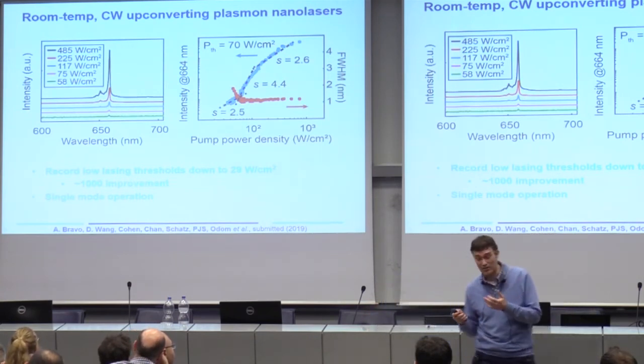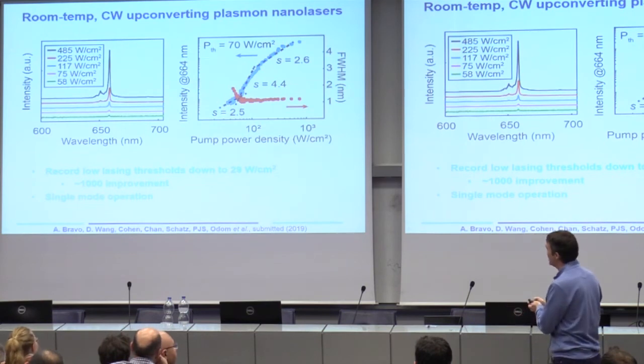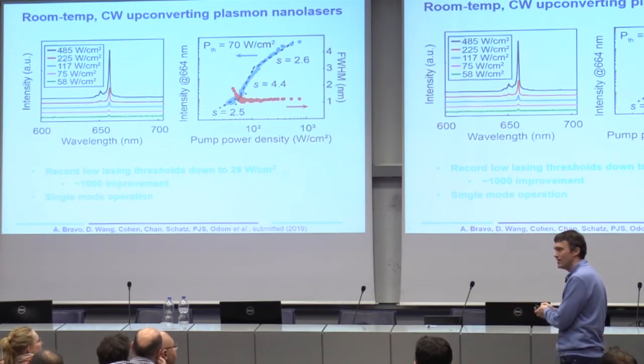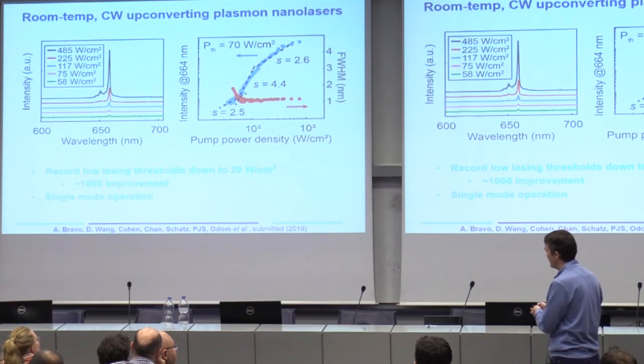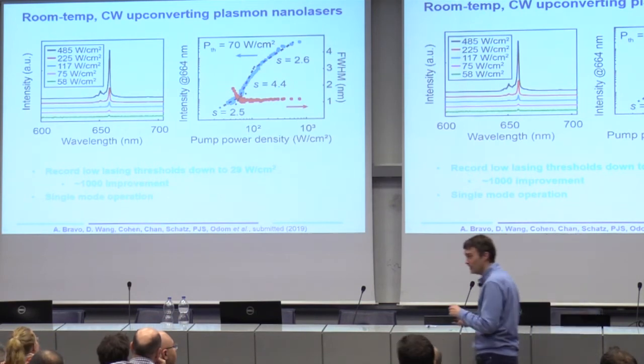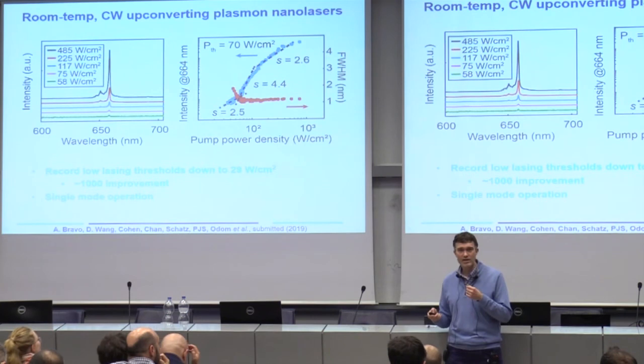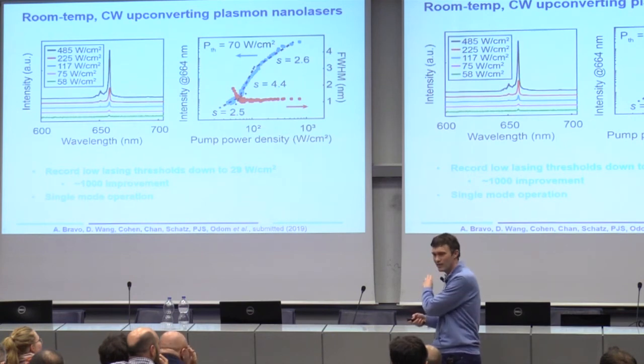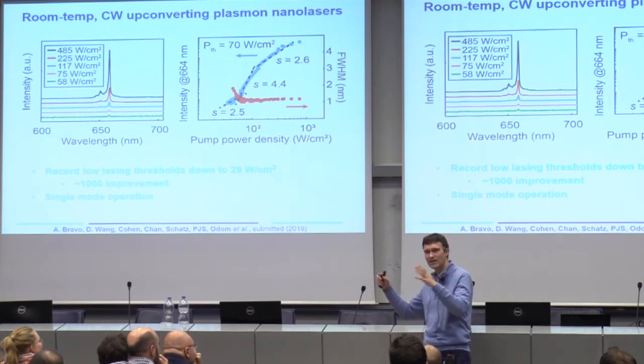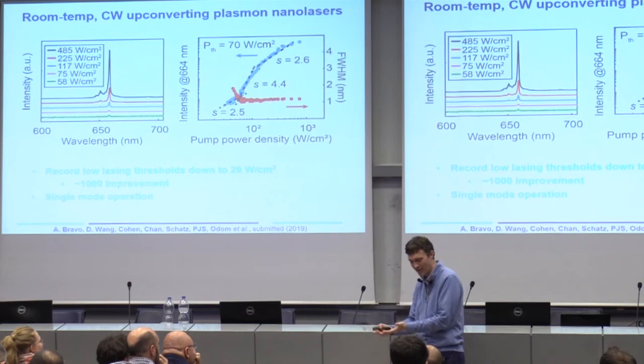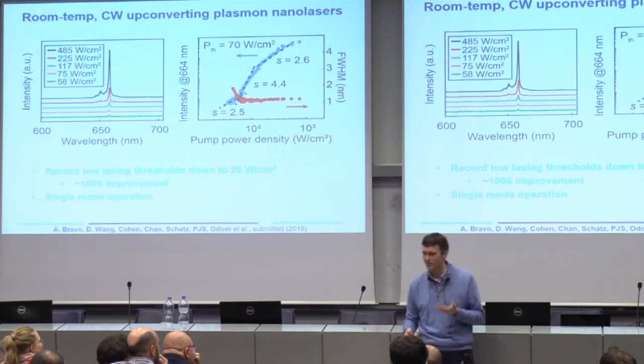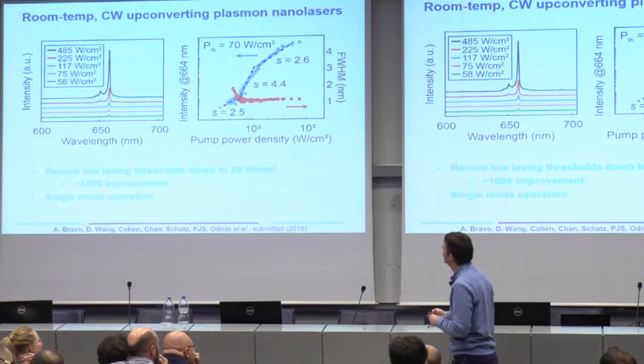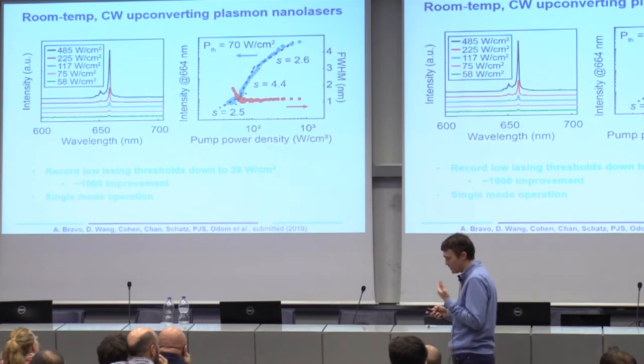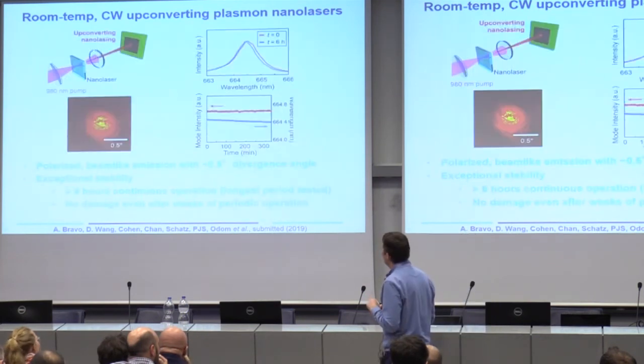But the thing that really jumped out at us was the lasing threshold. This is now 70 watts per square centimeter, and we had some that went down to as low as 29 watts per square centimeter. So for reasons that I can't explain right now, we improved the lasing threshold by 3 orders of magnitude. In fact, you're now getting close to the point where you can just take a big plastic lens and focus sunlight onto your array and make it lase. So a solar-powered upconverting laser, right? And this has us pretty excited.